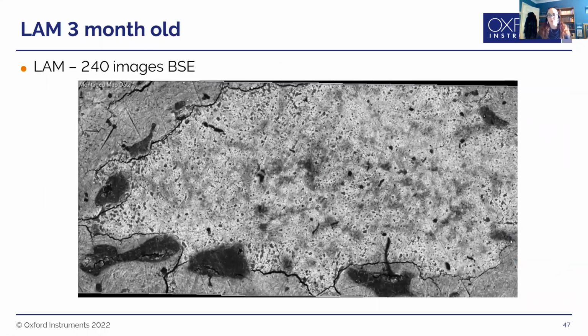Now this is 3 months old. So the implant has been embedded in for 3 months, and the model here was mini pigs. And you can see a difference between the implant and the bone. There is a density difference. There's also a crack that's running along that's due to the sample preparation process. But as before, identifying what actually is going on in the implant, what is biological material that's invaded the implant, what's happening to the biodegradation, it's really difficult to interpret from the backscattered data alone.